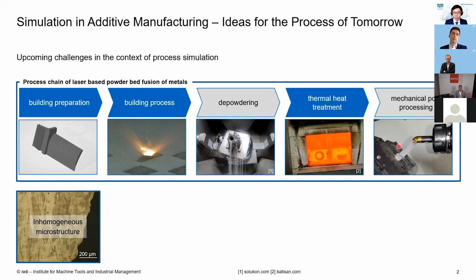But nevertheless, we are able to predict deformations, residual stresses. We also face different challenges in the context of process simulation. So for example, we have the inhomogeneous microstructure resulting from different geometrically induced cooling rates during the manufacturing process. And these cooling rates are mainly influenced by the assignment of different process parameters, which are assigned within the building preparation, so the pre-processing. Also, the microstructure can transform within the post-treatment. So for example, if we have a stress relief annealing process, we have creep mechanisms which are also resulting in additional deformation.